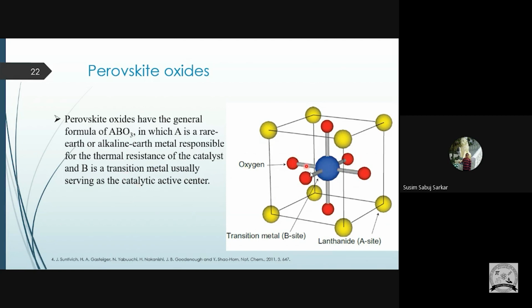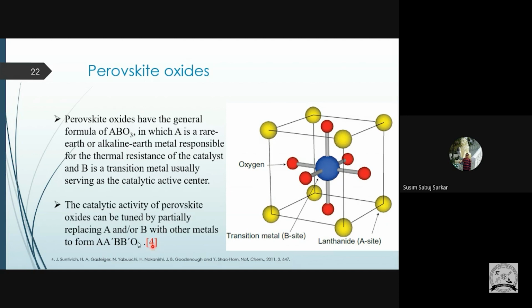So why use the perovskite oxide? Because this gives a sufficient amount of activity, and we can perform a very good catalysis with the perovskite oxide. Okay, so the catalytic activity of the perovskite oxide can be tuned, partially by replacing A or B in the middle, replacing A or B with other metals. That means mixing two perovskites, like AA'BB'O3. That will increase the catalytic activity of the oxide.